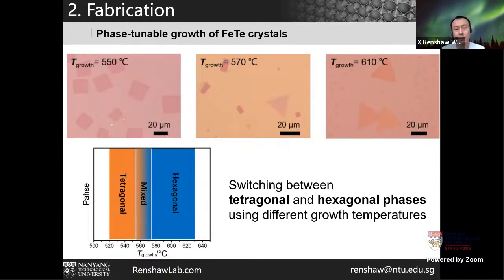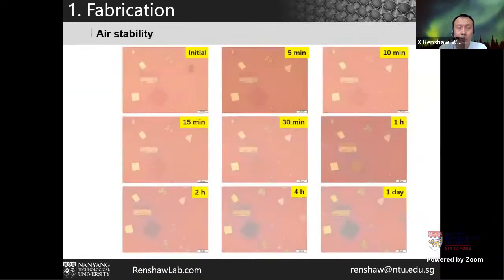So to summarize, basically using CVD by playing with the temperature, we can determine different growth phases, meaning we can control the phases. Now, if we know the phases, then the next step is naturally we want to investigate the properties. For the first step, we naturally need to see whether they are stable. So basically, we need to find out what is the window we can operate to study the structural property, magnetic property, or transport properties.